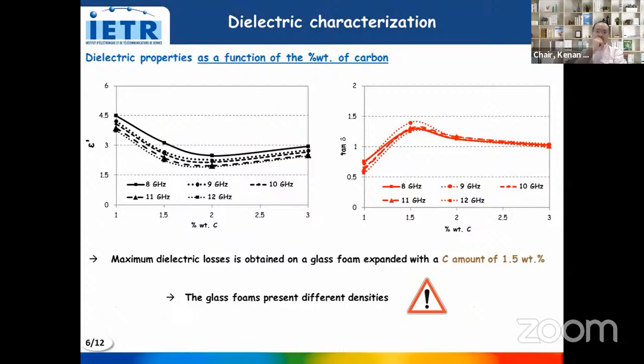Here I present the dielectric properties of samples as a function of the weight percentage of carbon, and we can observe that the permittivity decreases as a function of the carbon amount and increases for the higher percentage, and inversely for the dielectric losses. Maximum dielectric losses are obtained here for the glass foam made with 1.5% of carbon.